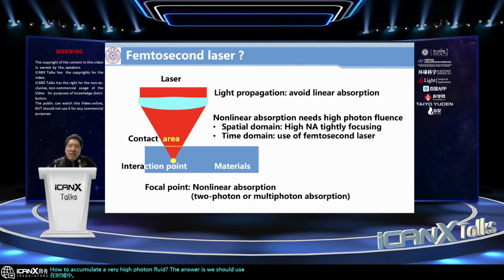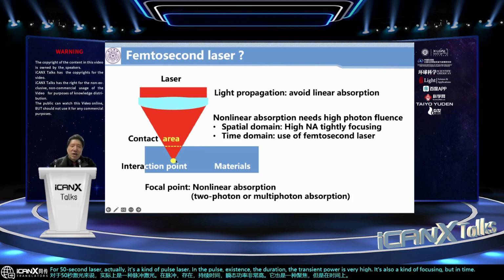The femtosecond laser is actually a kind of pulse laser. In the pulse duration, the transient power is very high. It's also a kind of focusing, but in the time domain. By doing this, we can accumulate very high photon fluence at the focus spot. Then the nonlinear effects or multiphoton effects may occur, not very difficult.